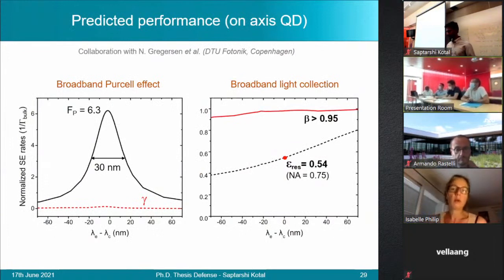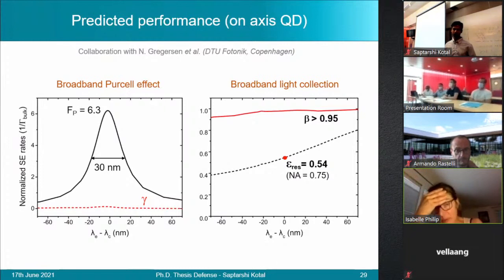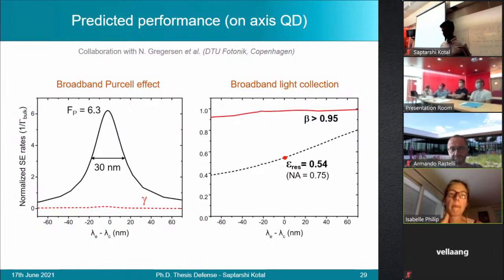Okay, this is something that always puzzles me a little bit. In fact, as you mentioned, you have a mode in your system, your nanocavity, whose line width is about 30 nanometer. And gamma is rather constant, whatever the detuning between the emitter and the cavity. But if we go to the beta factor, it's constant. And this puzzles me a little bit. I have difficulties understanding how you can have a resonance in the lifetime and a constant beta. For me, this is contradictory. I would have expected to have also a resonance in the beta. I don't understand why beta is constant.